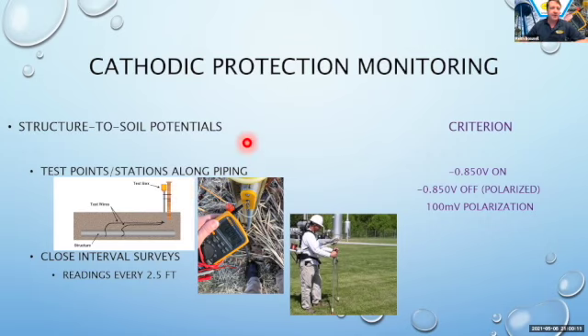They can also utilize any valves or above ground appurtenances, as long as they can make a metallic connection to the structure, so we can get a single point reading at that location. So here's an example of not really the test station at VMT, but a typical test station. There's wire brought into that conduit to the post, and we can take a reading.